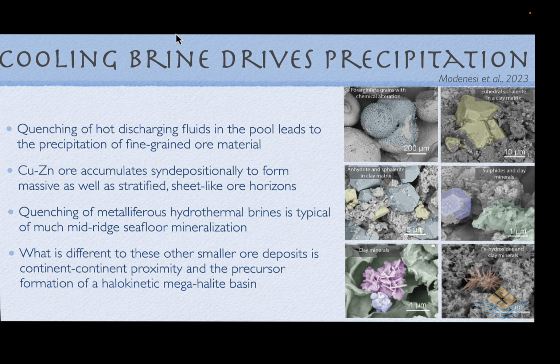Quenching of that hot discharging fluid, cooling of that fluid, leads to the precipitation of fine-grained ore material, along with other phases as well, silica and so on. And so we see copper-zinc ore accumulating syndepositionally to form massive as well as stratified sheet-like ore horizons. Once again, this is a contrast with the classic sedimentary strata-bound copper deposits, where we have epigenetic, diagenetic formation of the sulphides. Here it's syndepositional, not epigenetic, and it's created by quenching of a metalliferous hydrothermal brine.